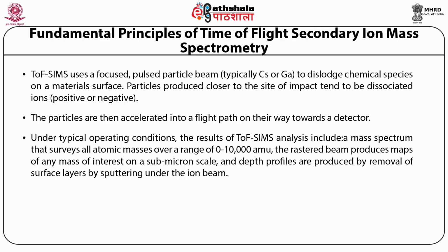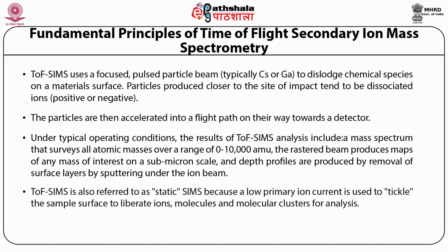The rastered beam produces a map of any masses of interest on a submicron scale, and depth profiles are produced by removal of surface layers by sputtering under the ion beam. TOF SIMS is also referred to as static SIMS because a low primary ion current is used to tickle the sample surface to liberate ions, molecules and molecular clusters for analysis.